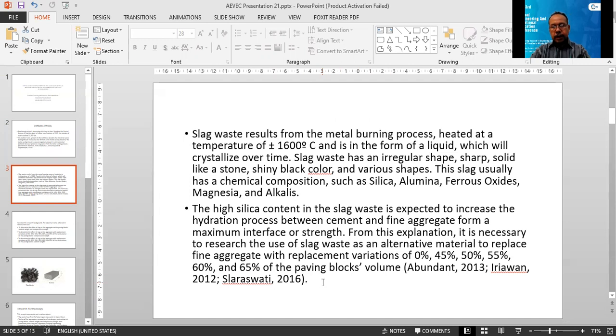Slag waste has an irregular shape, sharp, solid like a stone, shiny black color, and various shapes. This slag usually has a chemical composition such as silica, alumina, ferrous oxides, magnesia, and alkalis. The high silica content in the slag waste is expected to increase the hydration process between cement and fine aggregate to form a maximum interface or strength.